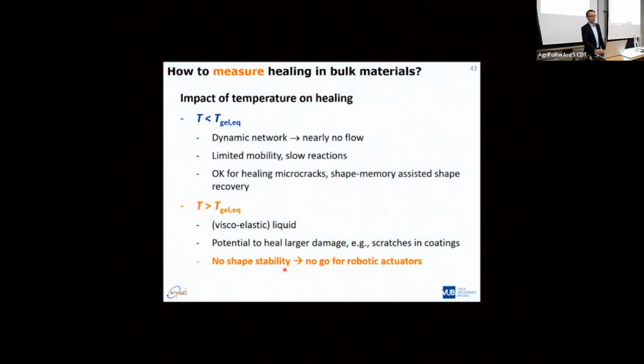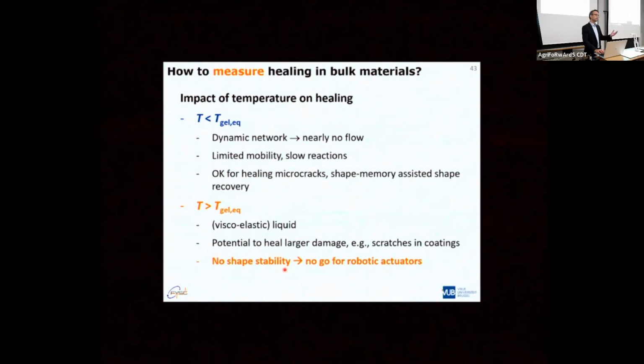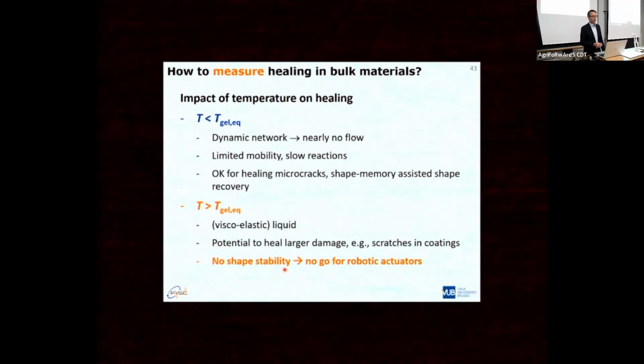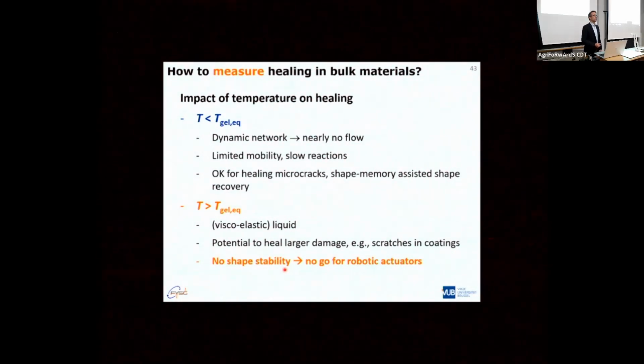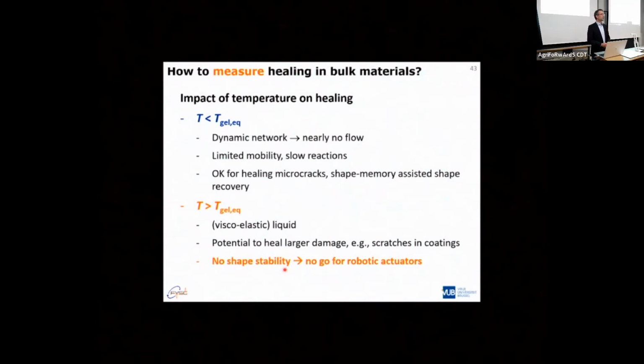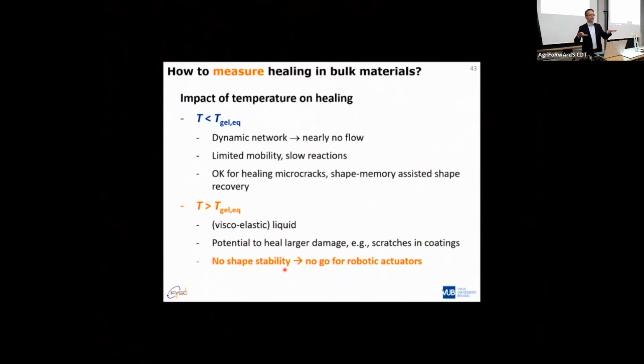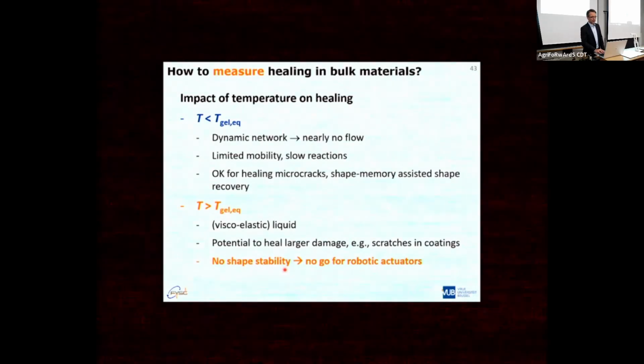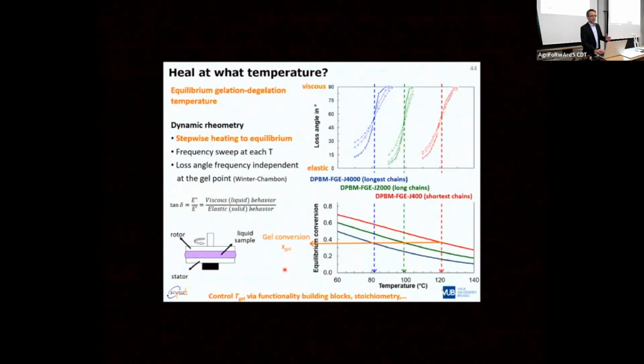In our case, there is a very important effect of temperature on the healing conditions. We talked about damage and so on, but of course, there's also, in our case, healing time and temperature and cooling rates that will be important. In our case, the gel temperature is a very important one. When you go above it, the material will start flowing. Then it's, of course, easy to close large cracks and so on. But for an actuator, that's not what you want to do. Accidentally, sometimes it happens that the furnace goes a little bit out of control. As a result, your temperature goes 10 degrees above the intended temperature and your actuator flows away. You get a puddle of elastomer rather than a nice bending actuator. So also these properties you will need to measure to know in which conditions the healing should be done.